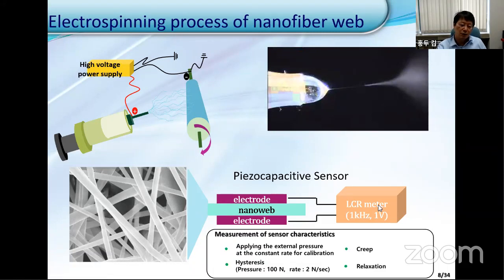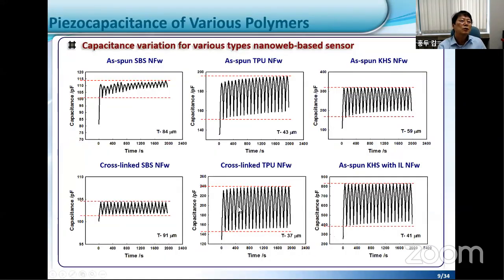During the measurement, we applied external pressure at a constant rate for calibration, something like 100 Newton, at 2 Newton per second. Also, we can measure the creep behavior and the relaxation behavior as well. This is one example. As you know, SBS is a well-known polymer, which is very elastic, but for our purpose, it's not as good. If I apply about 100 Newton, the red line, the distance between the electrodes changes, so the capacitance changes, as you see here.